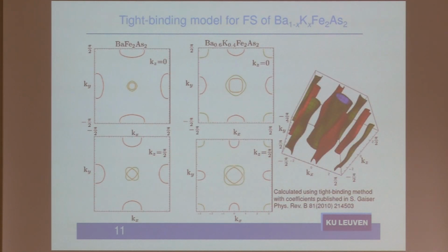First of all, we need our electronic structure. It is parameterized by tight binding from LDA calculations. They are known, for instance, for this kind of optimal doping. There was a calculation of this. The parameterization for this was extracted already, and we use it for 0505. So this is how it looks. We obtain different Fermi surfaces, a bit different. This is in a rigid band scheme. So what we obtain is this Fermi surface.